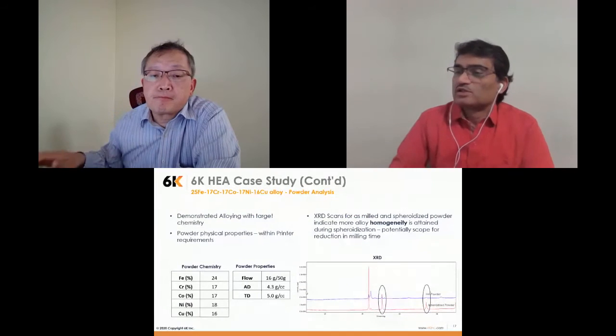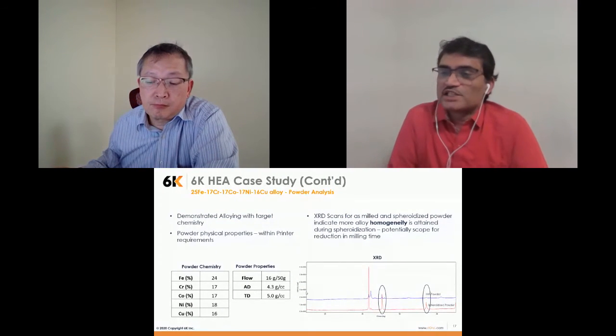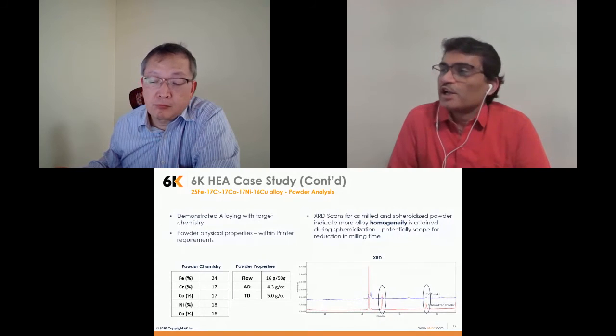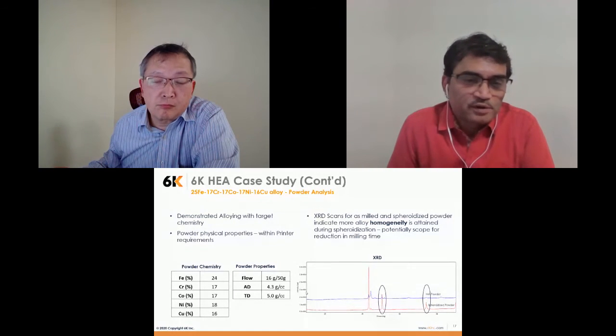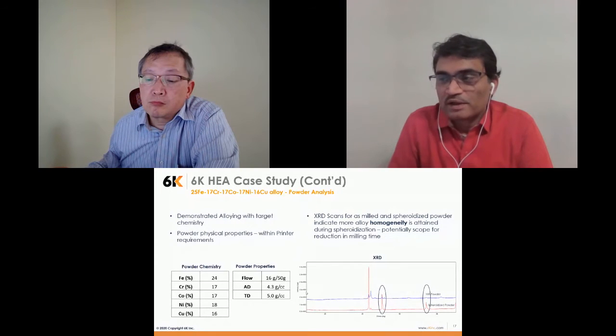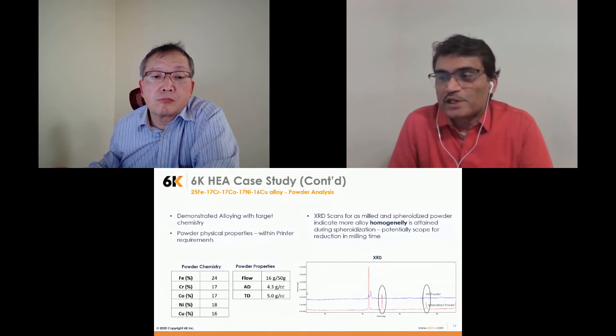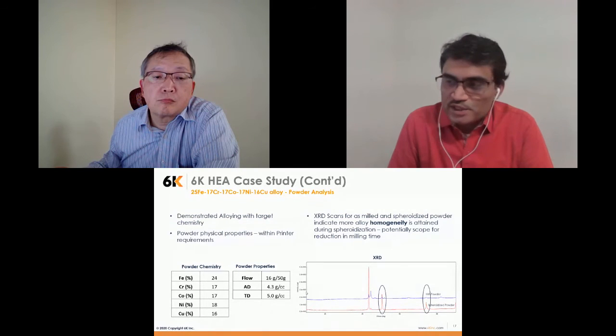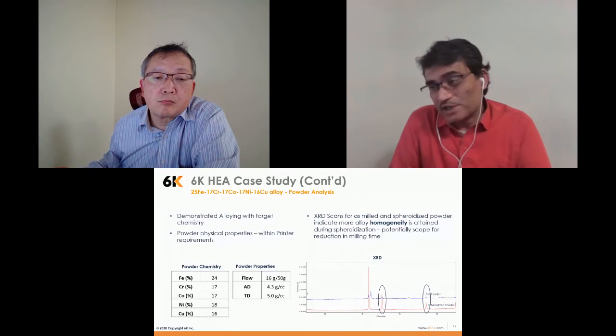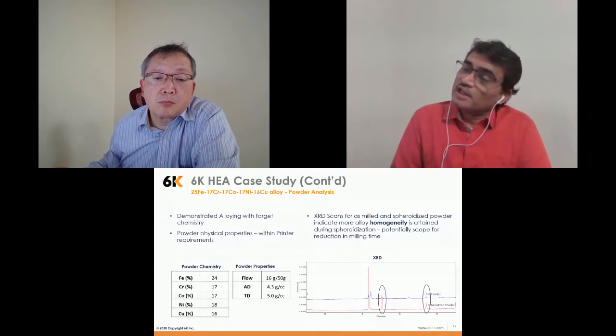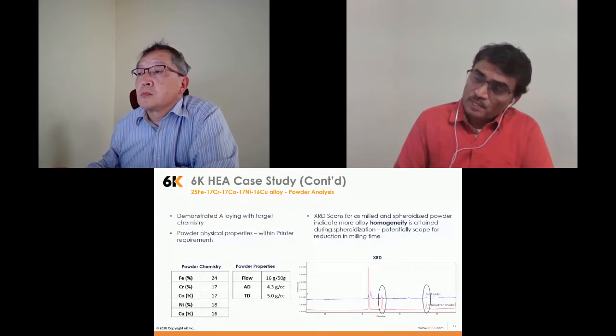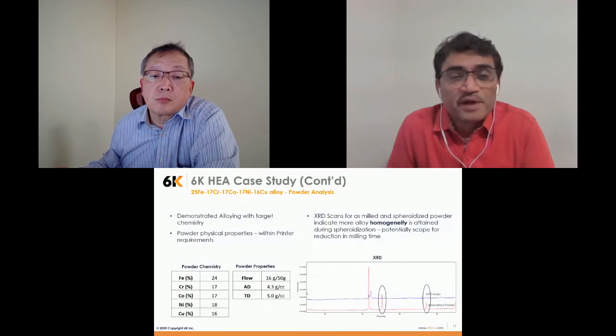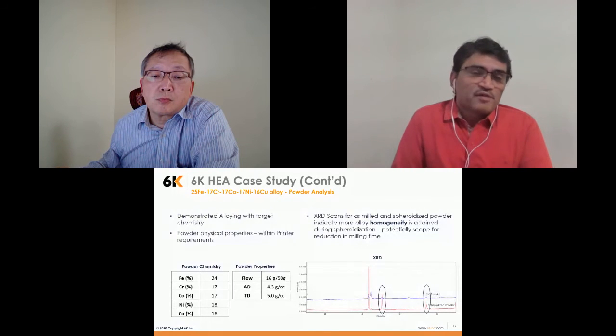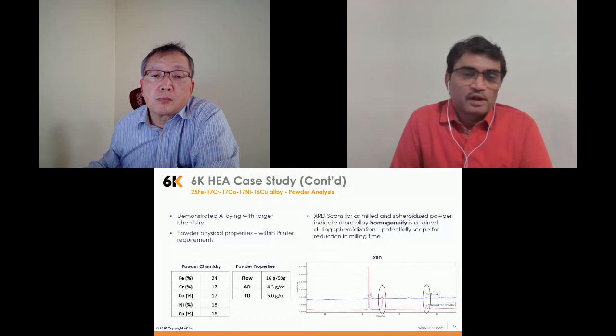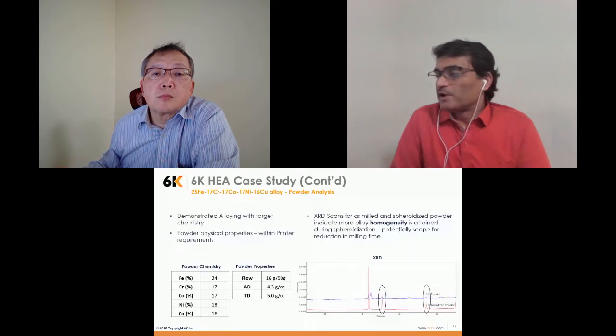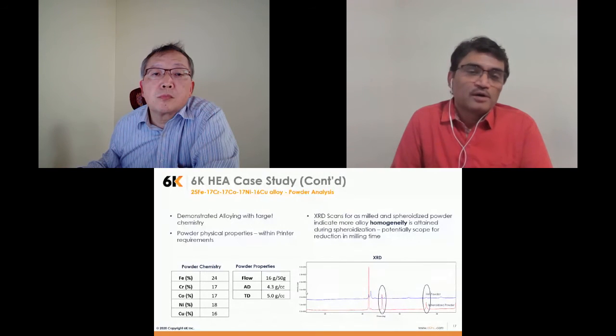So these are the analytical results for the HEA powders, or spherical powders, that were produced for demonstration. And as you can see, the powder chemistry almost matches the targeted chemistry. And powder physical properties like flow, AD, and TD are also in line with the requirements of additive manufacturing. One of the important things that we have noticed is that by spheroidizing, we can actually homogenize the alloy more.